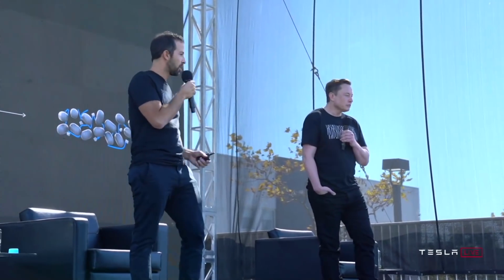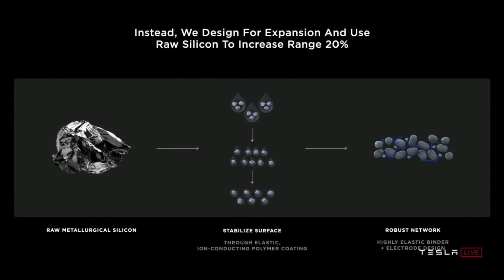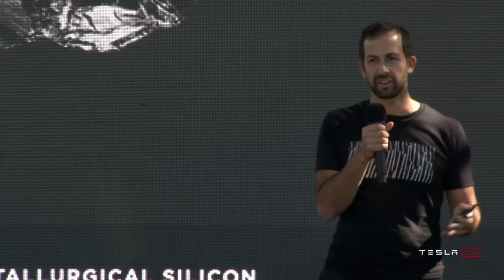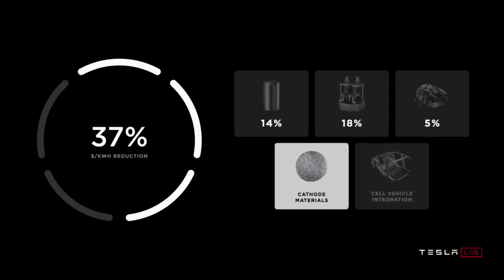And how does it work? Start with raw metallurgical silicon, stabilize the surface with an elastic ion-conducting polymer coating that is applied through a very scalable approach. No chemical vapor deposition, no highly engineered, high capex solutions, and then integrated into the electrode through a robust network formed out of a highly elastic binder. By leveraging this silicon to its potential, we can increase the range of our vehicles by an additional 20%, just this improvement. Yeah, it gets cheaper and longer range. And when we take that anode cost reduction, we're looking at another 5% dollar per kilowatt hour reduction at the battery pack level. And there's more.